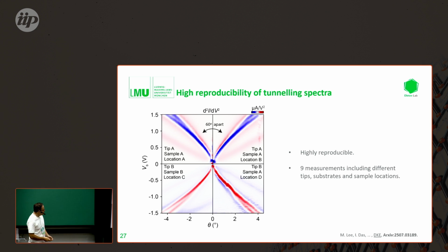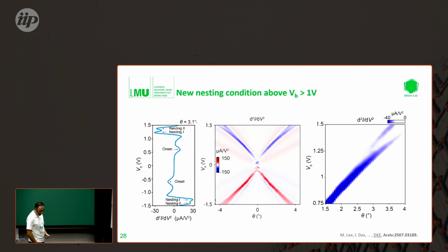Okay, for the last 5 minutes, I just want to show some unexpected results that we observed while we were getting warm with this technique. One thing we observed at relatively high bias, at around 1 volt applied to the device, is that the nesting condition, as you can see, started splitting. There are basically 2 nesting conditions that it forms, and you can also see it here quite nicely, where the main nesting condition fades away and then there's a second one branching out of this.